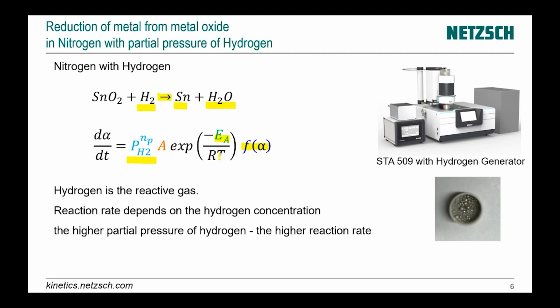We have the reaction rate, and the pre-exponential factor, which depends on the total pressure. And here we have the partial pressure of hydrogen and the exponent for the partial pressure of hydrogen. We will put an arbitrary value here, which will be optimized during our fit. According to stoichiometric coefficients, it should be 1 here, but in reality for solid reactions the order of reaction is not always equal to the coefficient from our chemical reaction, and therefore we just put an arbitrary value.